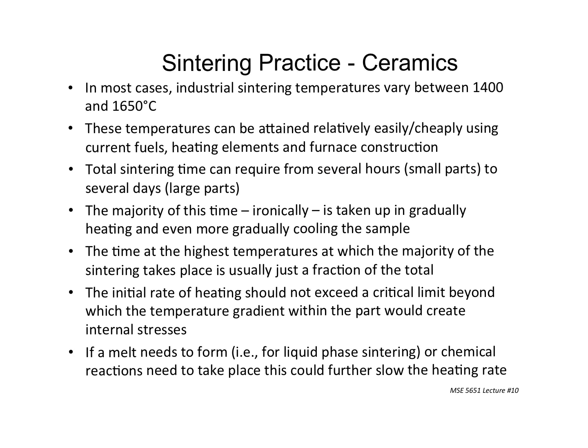Okay, so in most cases, sintering temperatures vary between 1400 and 1650. All right, if you can get there cheaply, that's awesome. Total sintering time can vary from several hours for small parts to several days for really large parts. And the majority of this time is taken up in gradually heating and even more gradually cooling the sample. So we always think about sintering as that high temperature point, but a lot of the time involved is that slow crawl up and the slow crawl down.